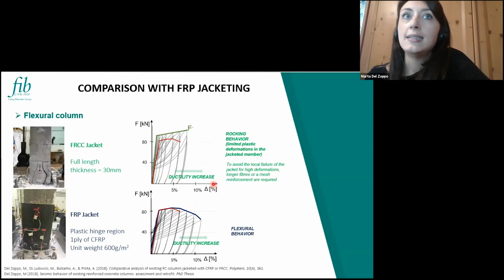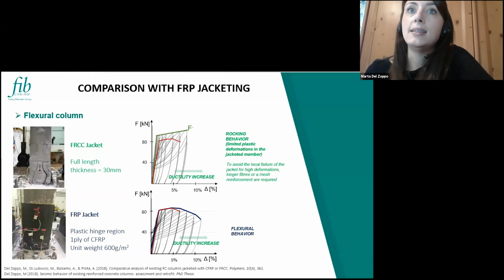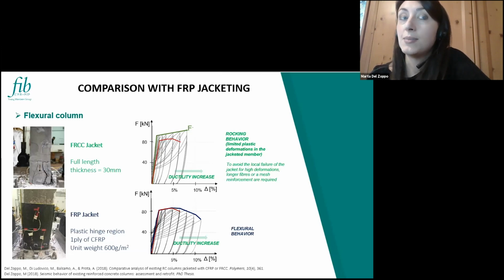While in the case of the FRCC jackets, we have this slight increase in lateral stiffness. In this case, we have also a slight increase in flexural capacity, and this is related to, of course, the slight cross-section enlargement that we are doing when we apply such kind of strengthening solution. And we have this increasing behavior until the sudden failure of the jacket. So if you want to have more deformation capacity and some more ductility, we need to probably adopt longer fibers to avoid the sudden failure after the opening of the jacket, or adopt additional mesh reinforcement to use such a system as a confinement technique.